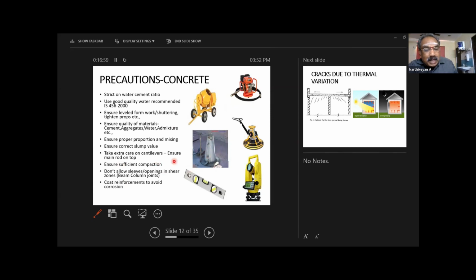Extra care for cantilevers. Ensure main rod on top. We know in cantilevers the main rod should be on top. Yes, people provide it, but they forget to provide chair rods. Chair rods are small bent-up rods to be placed. People walking on the cantilevers may make the cantilever rods bend. Instead of the rod being in the tension zone, it comes to the compression zone. People pour the concrete without knowing this properly, and then there is a bend, there are cracks, and sometimes accidents happen, as in one of my sites.